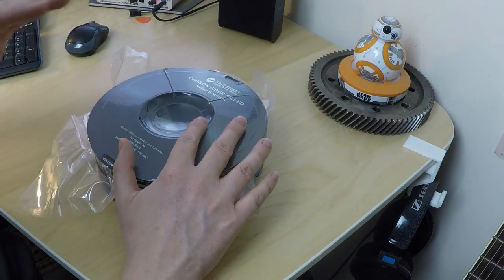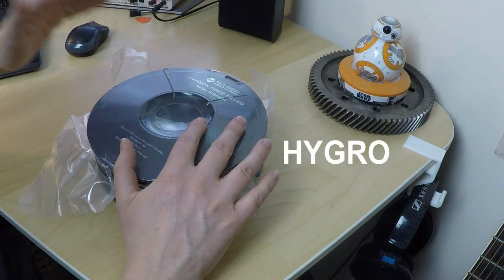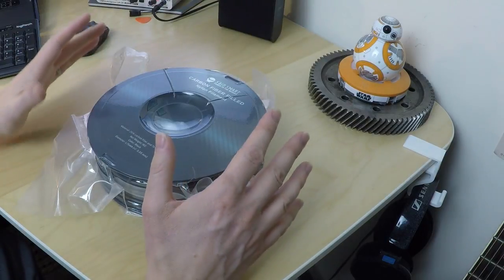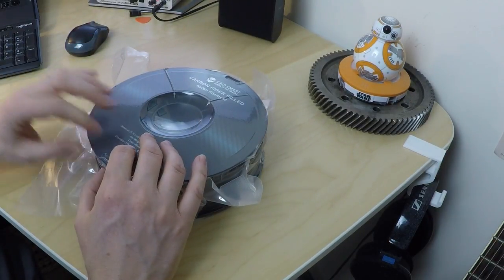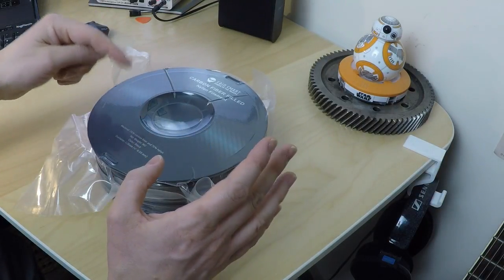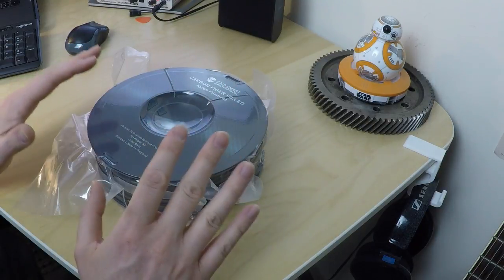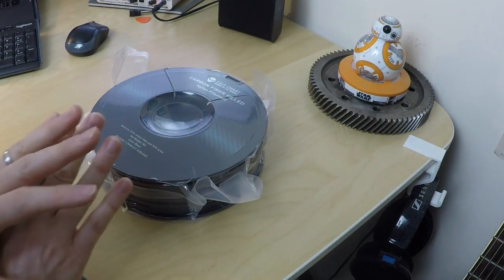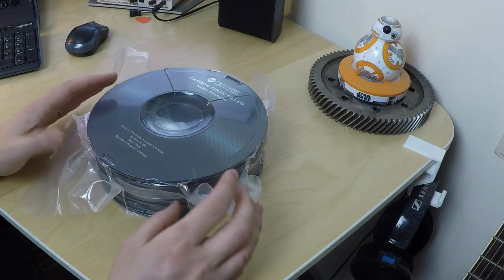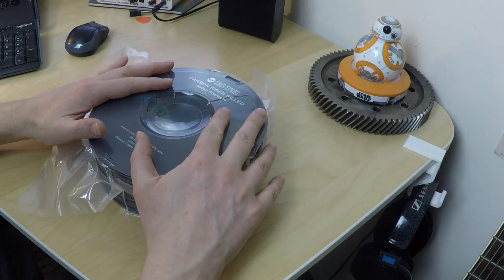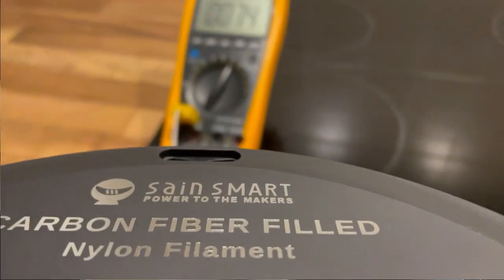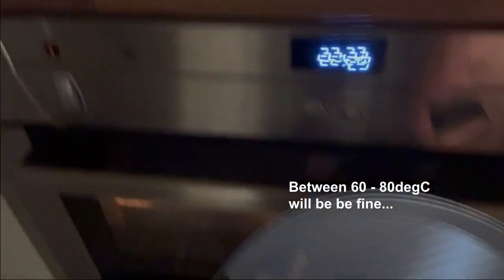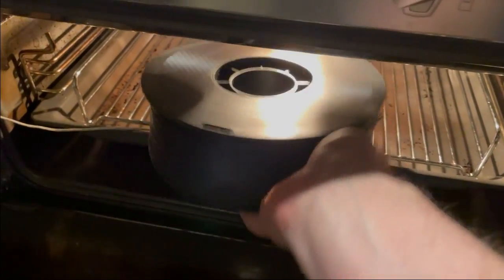So nylon, very hygroscopic, which means it absorbs moisture. So you put that moisture within the filament through a hotend at 250 degrees. Suddenly you've got part 3D printer, part kettle. Bad times. So you need to dry the filament out so there's little to no moisture inside at all. And this is worth doing every time before you start printing. So I've got a fan oven that maintains a nice easy 60 degrees centigrade. So four hours in there and it's ready to go.